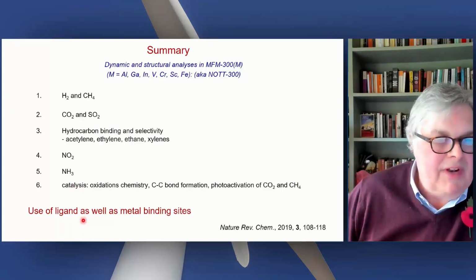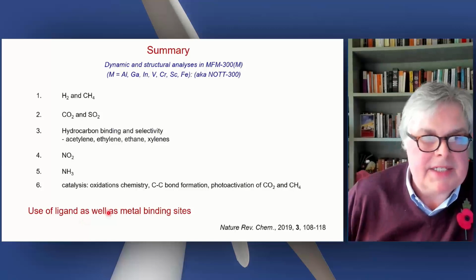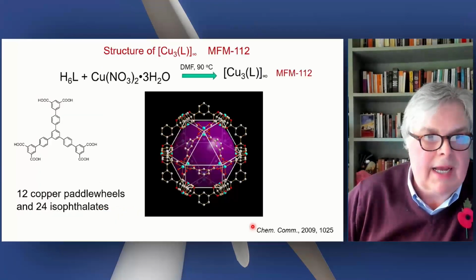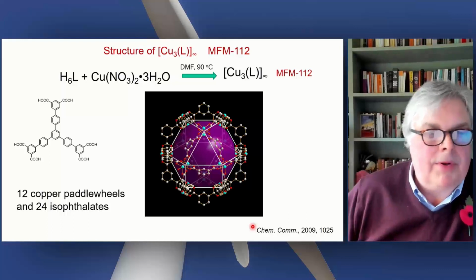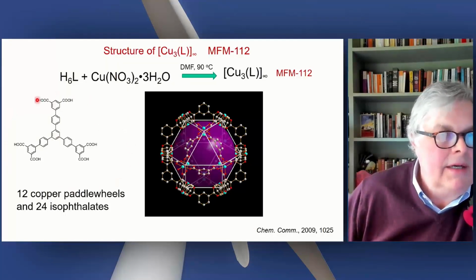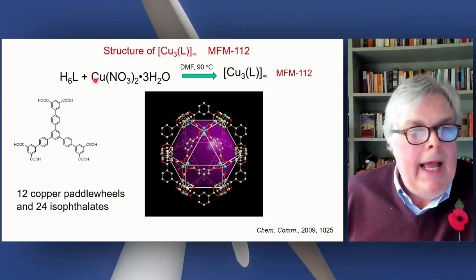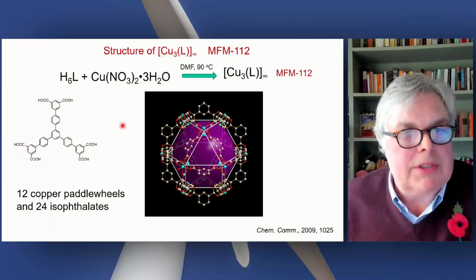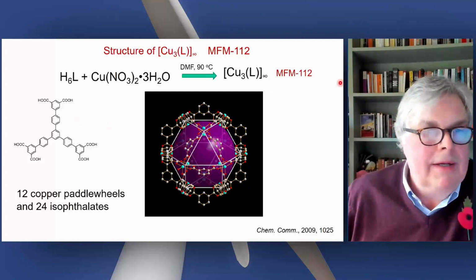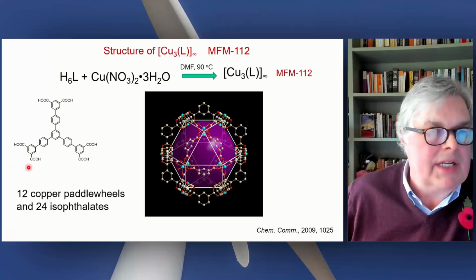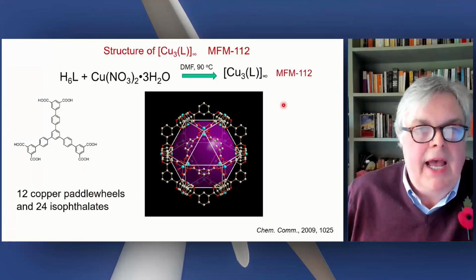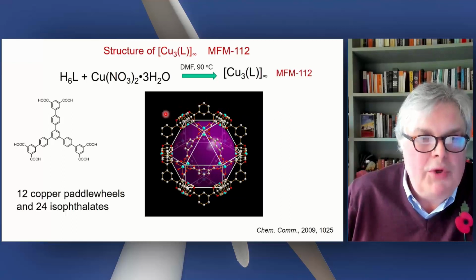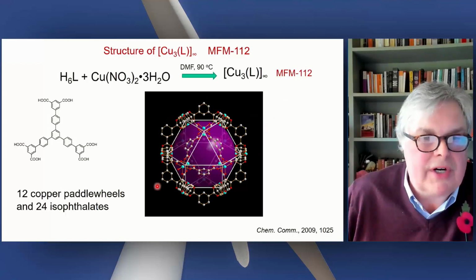I emphasize the use of ligand as well as metal binding sites, and some of this work was reviewed a couple of years ago. So as an example, you take this hexa-carboxylic acid ligand, which of course you have to prepare, react this with copper-2 salt, and you end up with a polymer, because clearly each of those carboxylates will coordinate to a copper center, and you form a three-dimensional structure which incorporates this copper paddle wheel structure with 24 isophthalates. This is an isophthalate coordinated.